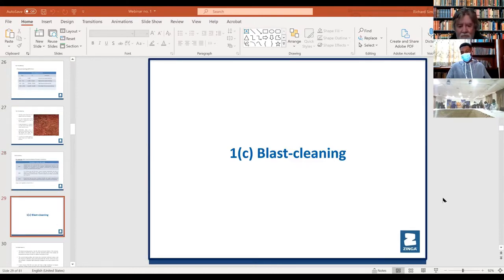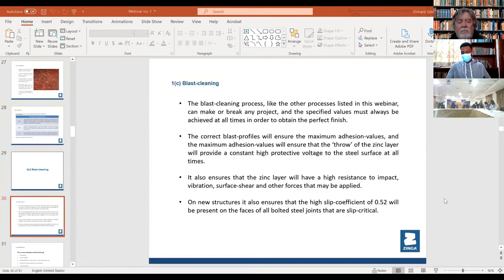Okay, we come to blast cleaning now, which is one of the keys. Bad blast cleaning can make or break any project. So it's an important step in those first four that we described. It's a very important one. The correct profiles will always ensure that you have the maximum adhesion values of the zinc. And just in case you don't know, when you apply Zinga onto a good blast profile, after 7 days, you will have roughly about 6.4 megapascal of adhesion strength. After 3 or 4 months, it goes up to 9 megapascal. And after 1 year, it goes up to 11. So it's getting tougher and tougher with age. And it reaches 11 megapascal after roughly a year.